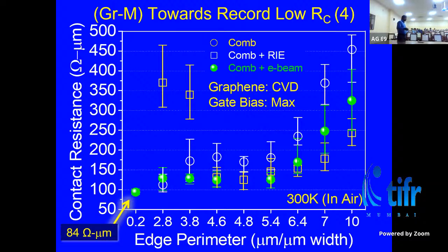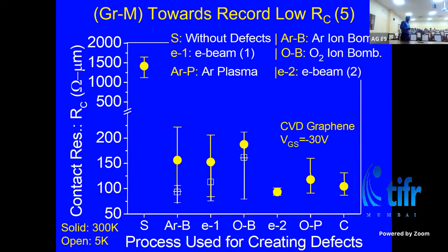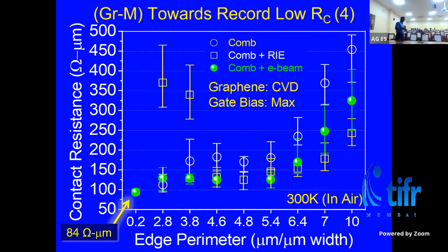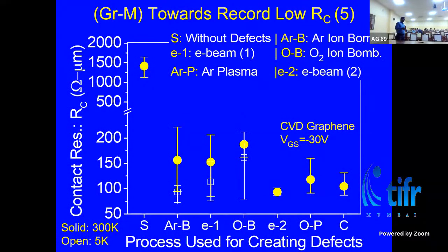Now, this is a little old chart. Our latest numbers with some other metrics are now 36 ohm micrometer. Right. We have not published that, so that's why we have not included that data here. Now, this is the record low contact resistance that we reported, and even compared to other numbers, this is the record low contact resistance. And now what you see is, as a function of different processes, what is the best contact resistance we get. So this is the standard.